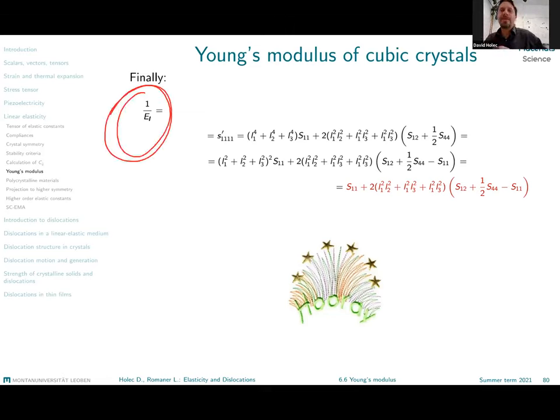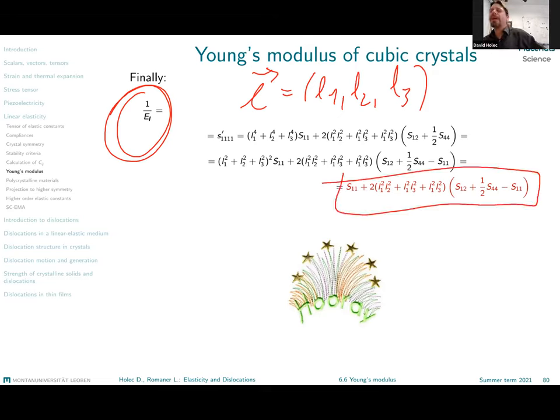How is the Young's modulus in a given direction L, once again vector L, L1, L2, L3, related to the compliance matrix components? You see that this is an easy analytical formula, and now you can visualize those simply by running through all values L1, L2, and L3, probably by keeping those as a normal vector, because that's the definition of the cosines here. Then we can visualize the directional dependence of the Young's modulus.